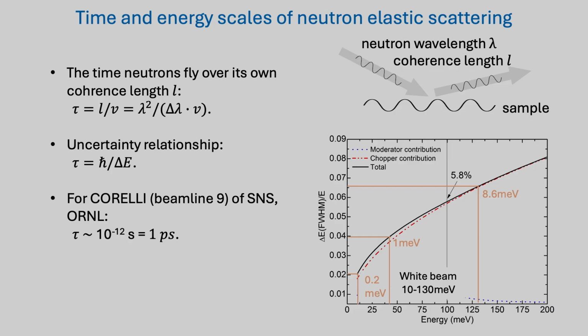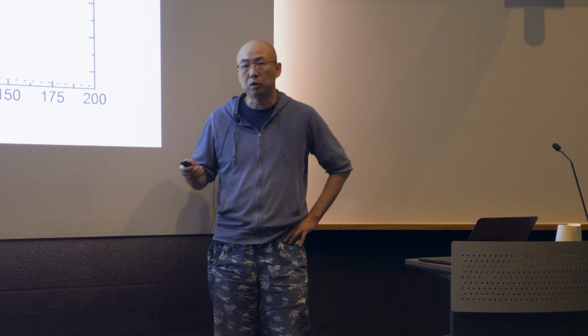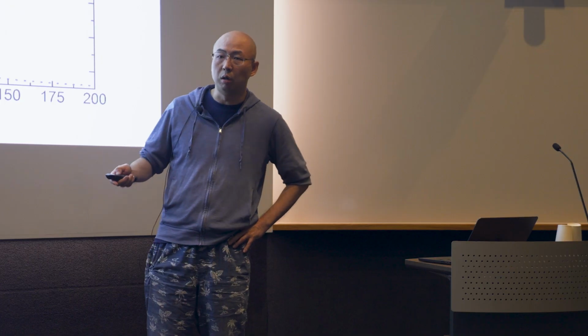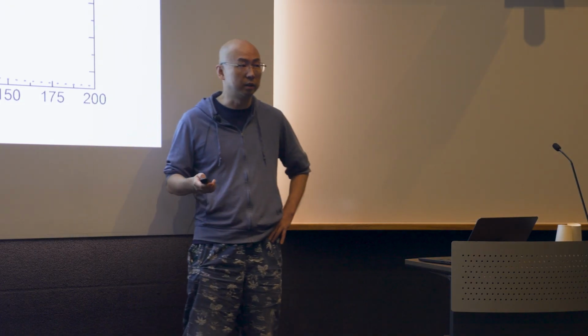And this is actually very easy to calculate. And the alternative way to calculate it is actually to use the energy uncertainty of your neutrons, which is specified by the beamline itself. So we know this value very well from the construction view. So with that, for the specific neutron beamline we used, you get a time constant of 1 picosecond, 10 to the minus 12 second. So that actually gives you a perspective about spin correlation in our disordered materials at this time scale.